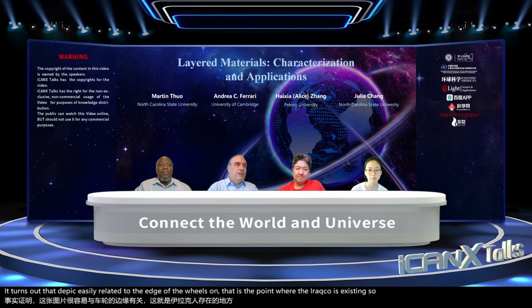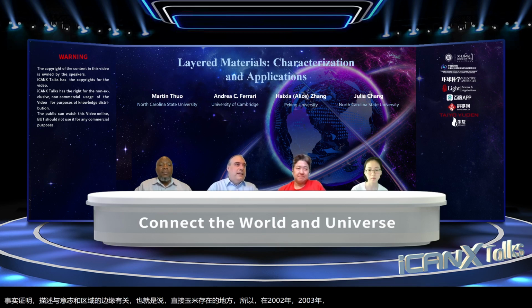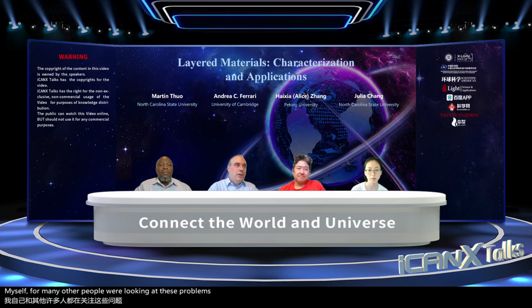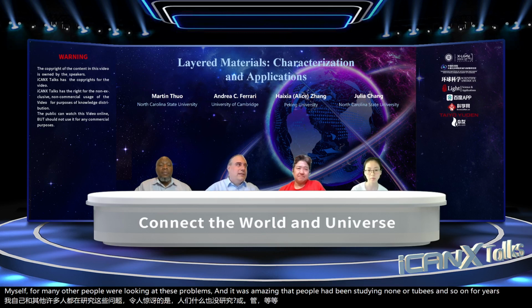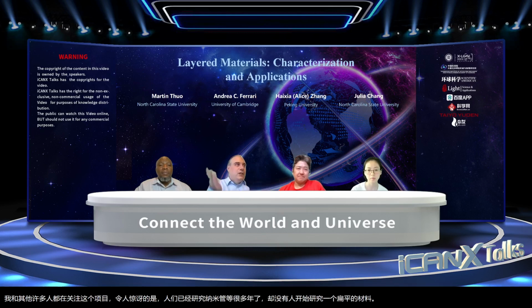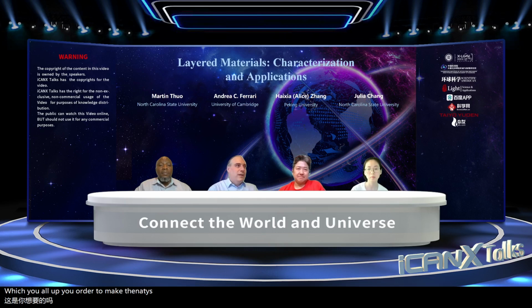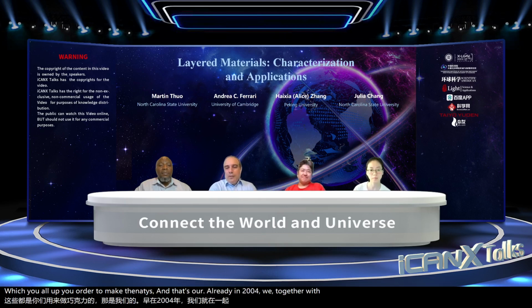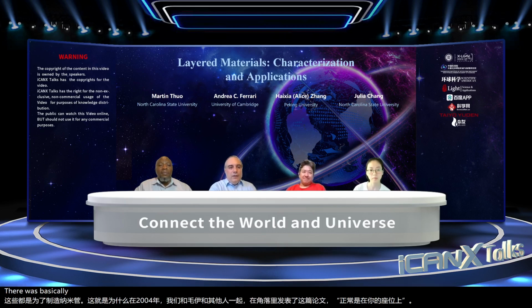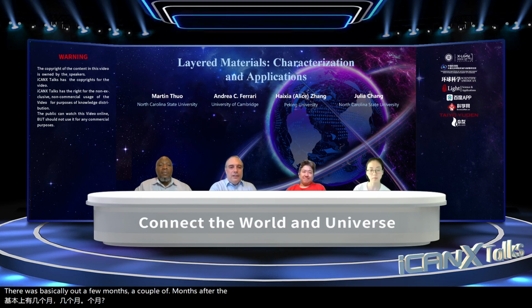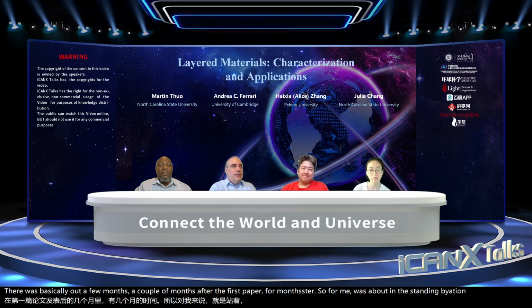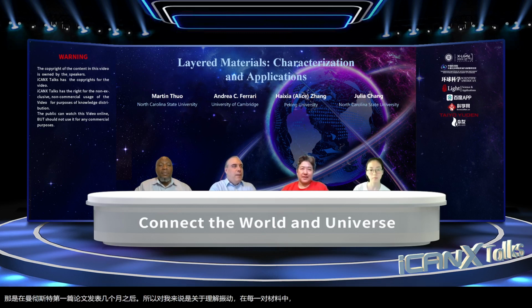So already in 2002, 2003, myself and many other people were all looking at this problem. And it was amazing that people had been studying nanotubes and so on for years, and nobody studied the flat material, which you roll up in order to make the nanotubes. And that's how already in 2004, we, together with Mauri and other people, published this paper on the Kohn anomalies in graphene that was basically out a couple of months after the first paper from Manchester. So for me, it was about understanding vibrations in every carbon material, in particular the D peak.